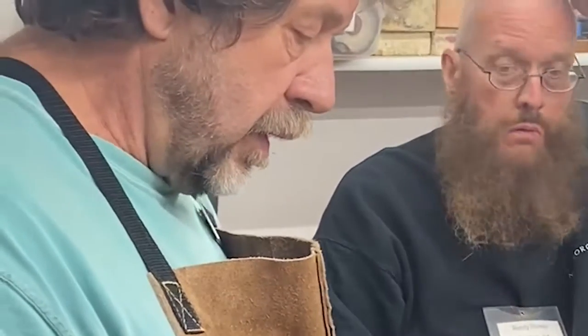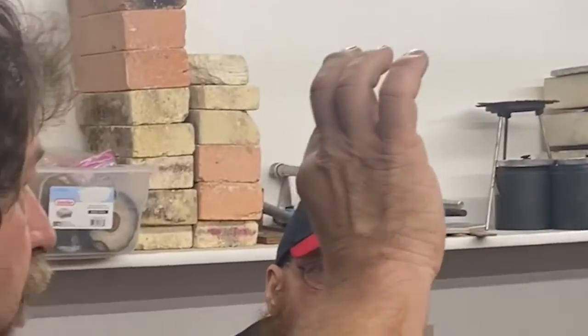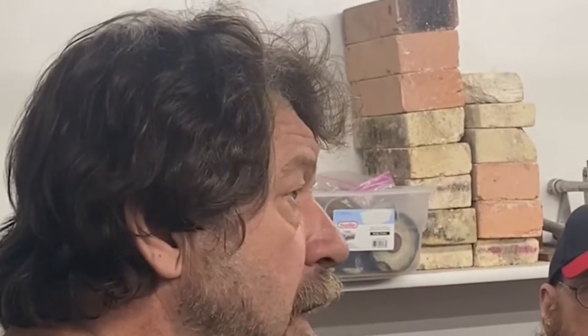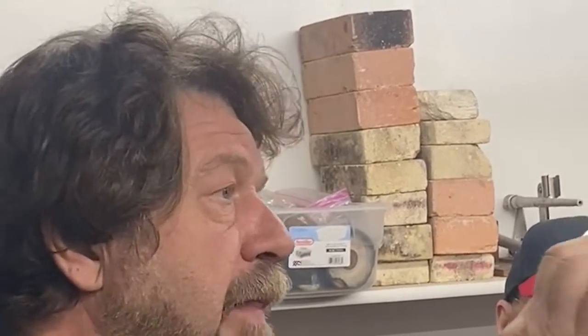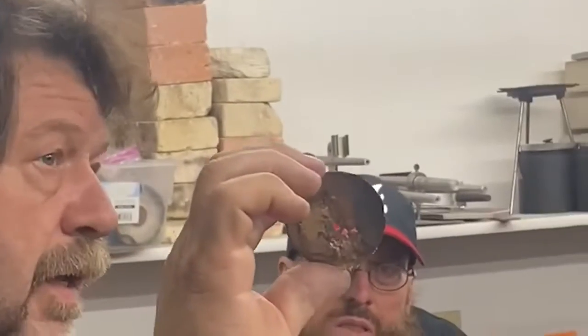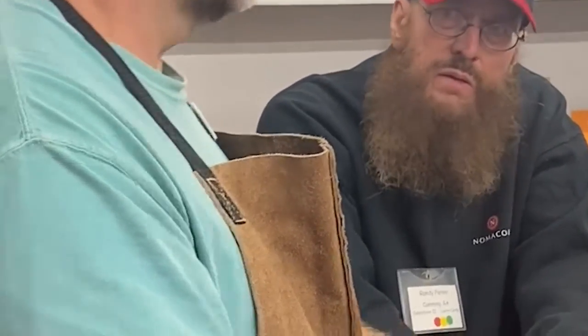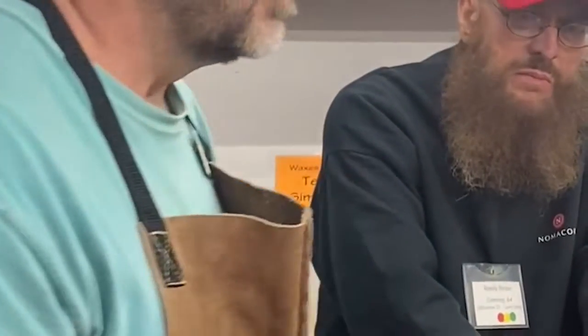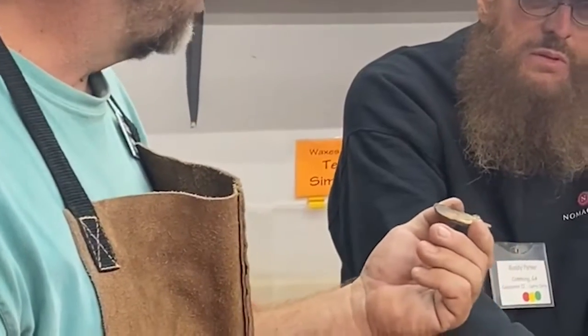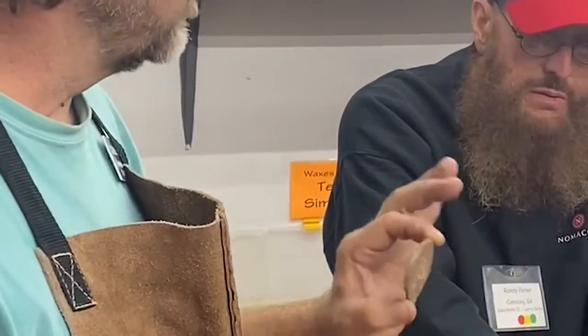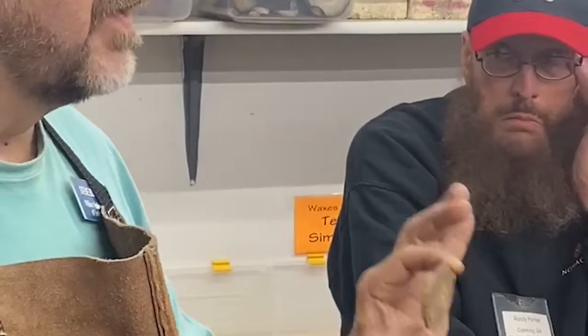What we try to avoid, and we do have the occasional mishap, is this: Emmett's Folly. He spent about 2 hours working on the wax and ended up with a mold of the back of the casting machine. Because instead of doming it, he poured a little too little investment in it, and the metal shot right through the mold. So, you know, that's sort of a bit of a mishap. And we keep that and show this to remind people. We don't want to do this.